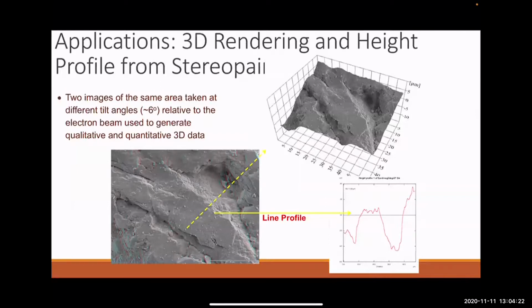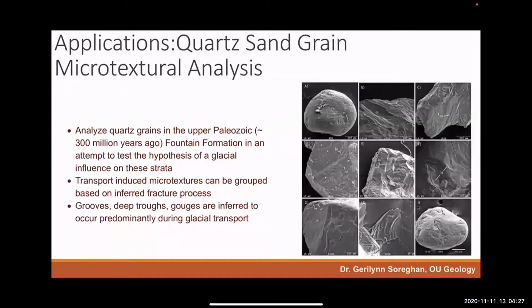Again, this is on a quartz grain, but SEM images are two-dimensional. So you can see a scale bar here, for example, this 200 microns, and that's the scale that's appropriate in the X and Y direction. So you can do particle sizing very easily, but it's a two-dimensional image, so you can't tell depth. So for example, on this image, looks like there may be a trench here, a little hole or trench in the grain. And you can infer that from the image, and you'd be right, but what you can't do is measure the height of that.